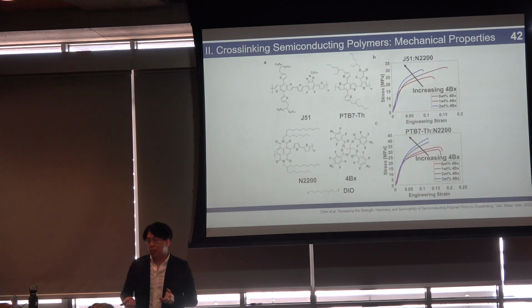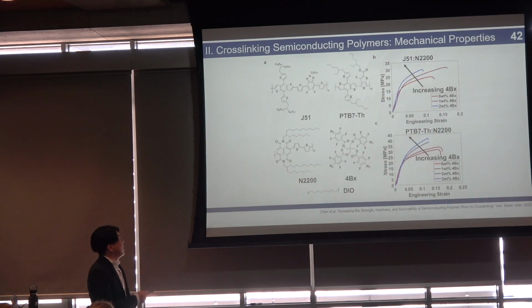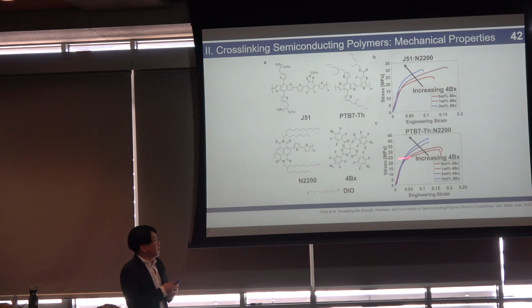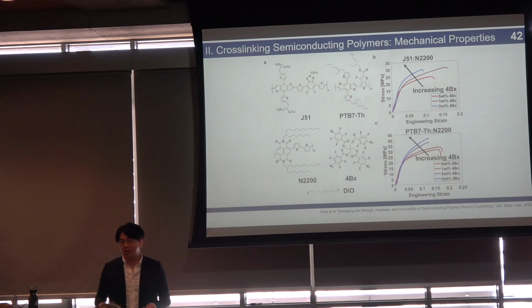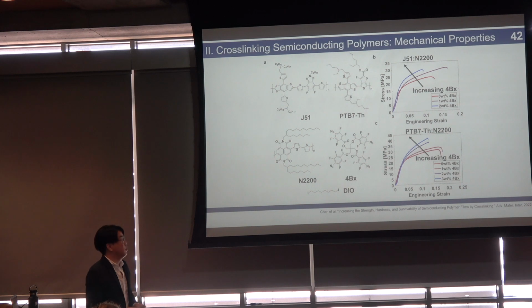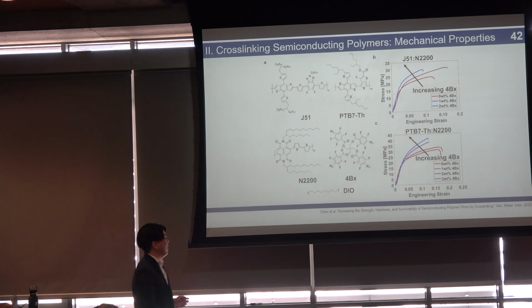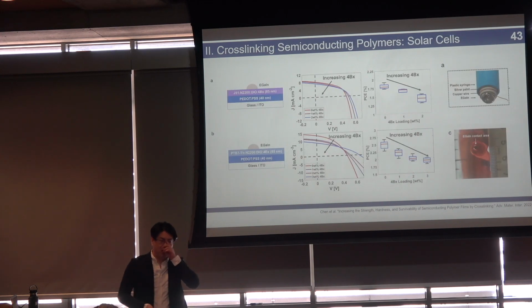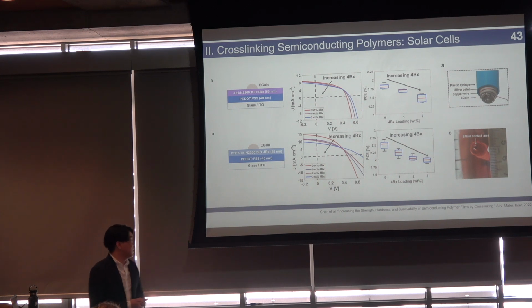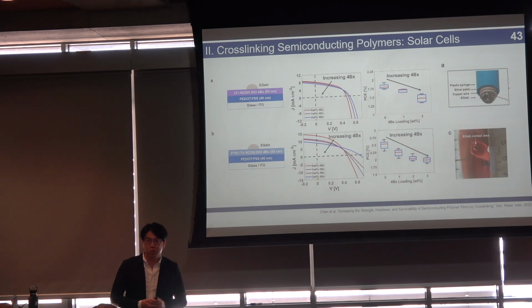So we explored a couple different bulk heterojunctions for this. We used 2 types of p-type materials and 1 type of n-type material. So we mixed J51 and N2200 together, and PTB7-Th and N2200 together. And first we looked at the mechanical properties, and we saw approximately the same thing. About 1 weight % seems to be the best in terms of optimizing the mechanical robustness. And we made solar cells with these. Or more specifically, I should say we made half-stack solar cells with these.